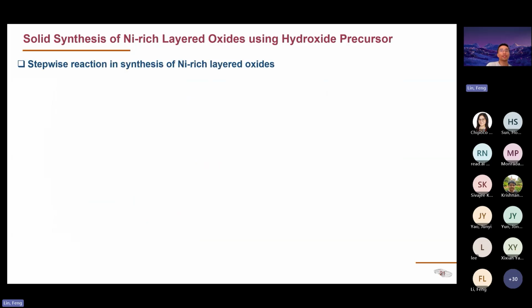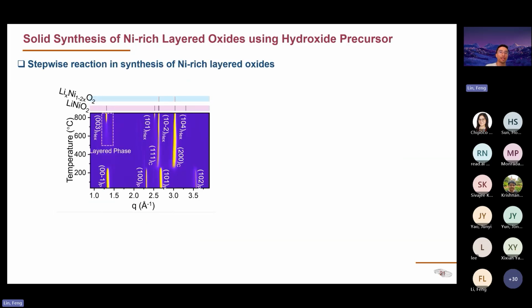So how does the synthesis happen during a normal process? This is an X-ray diffraction contour map of the phase change during the calcination. On the left-hand side here is the temperature axis. And you can see that we get diffraction peaks in the beginning. They are the precursor metal hydroxide peaks. And then as we go to higher temperature, it gradually transforms into the layered phase. From here, you can see the layered phase start to form at around 400 to 500 degrees C, and then get more obvious as you go to high temperature, like 800 degrees C.